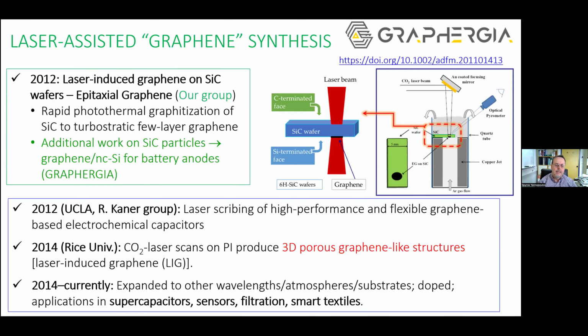In this slide, I try to summarize a few major milestones in the most modern development of the laser-induced graphene era. So in 2012, in our group, we used a CO2 laser and managed to prepare epitaxial graphene on silicon carbide wafers by a simple method which is shown in the schematic here. The method took place at ambient conditions, and it was based on the rapid photothermal graphitization of silicon carbide. The decomposition of silicon carbide removes silicon and the remaining carbon reconstructs to epitaxial graphene. And then later in our group, we extended this decomposition of silicon carbide to particles. And this opened the way toward the graphene-based battery anode concepts that we are using now in GRAPHERGIA.